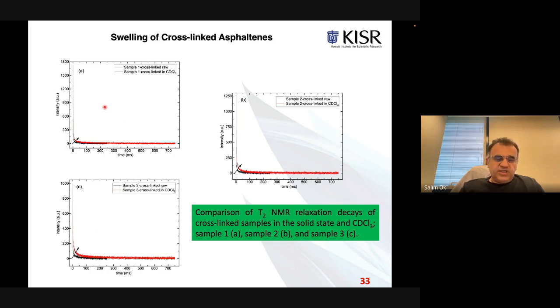So when we dissolve our asphaltene samples, or place our cross-linked asphaltene samples into deuterated solvents, we don't get any signal from the deuterated solvent, and rather all the signal we get is coming from our samples.